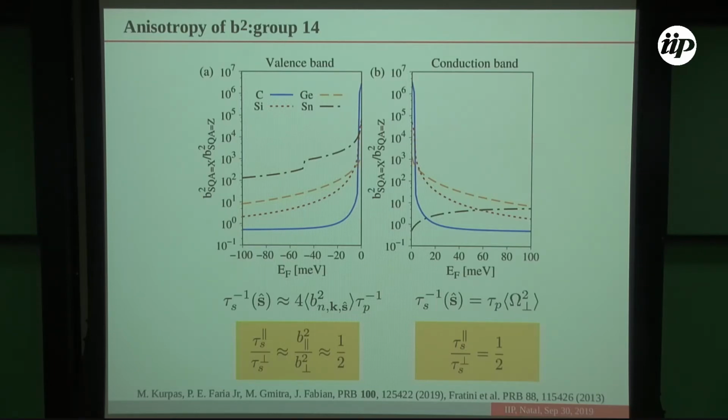So you would get the same dependence as for the diagonal parallel mechanism. I told you at the beginning that in flat graphene, spins don't relax. But if you break this mirror symmetry, by small rippling, for example, then we can enable the Elliott-Yafet mechanism. So I would say it's really surprising that we observe the same kind of anisotropy for intrinsic spin-orbit coupling as for the extrinsic one.